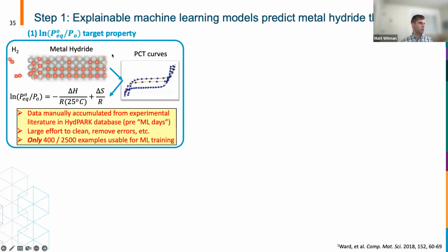So the first thing that we want to emphasize is that we can use these explainable machine learning models to directly predict these metal hydride thermodynamic properties. So again, we have this metal hydride. I explained how we collect the PCT curves, and from those PCT curves, we can extract the enthalpy and entropy of formation, which basically allows us to predict what the equilibrium plateau pressure will be. And that's the main thermodynamic property of interest for pretty much any application. It tells you what pressure you release hydrogen from your material at a given temperature.